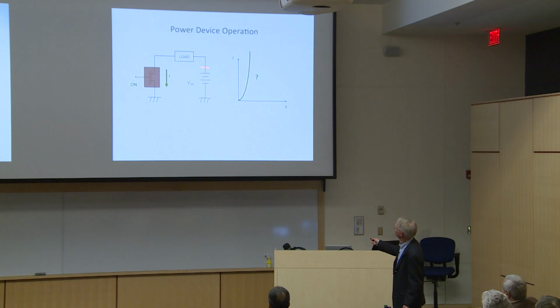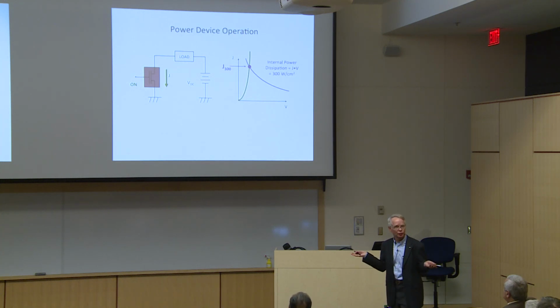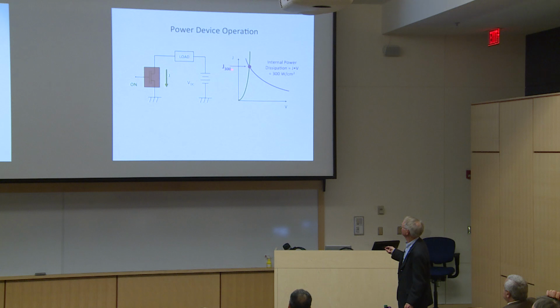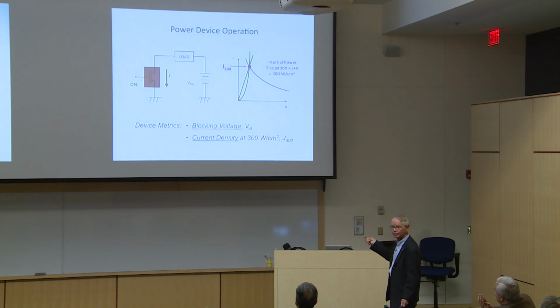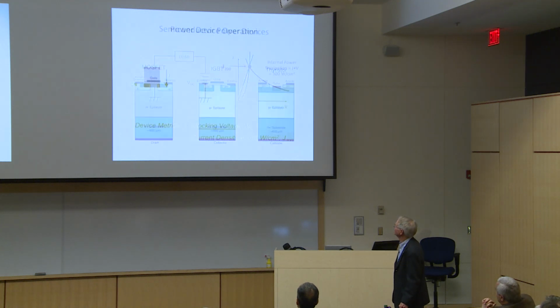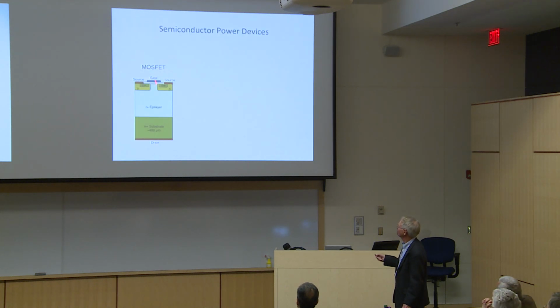Well, the power dissipation is just a product of the current times the voltage. So if I put a line here of constant power dissipation, it's going to be like a hyperbola. Now, I can operate up to this point. If I go any higher current, I dissipate too much power. So it turns out that we're going to look at the current that the device can carry at that specific power dissipation. Now, this parameter is good because it doesn't matter if the characteristic is nonlinear or if it's linear. I can quote that number and I can compare these two devices. So the metrics I'm interested in are the blocking voltage in the off state and this maximum current density in the on state.